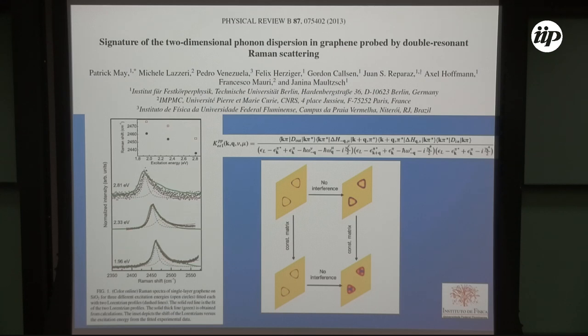And what I have in this calculation is only energy and momentum conservation. So if you take only momentum and energy conservation, you see this point. If you do the correct calculation, it disappears. So this is also related to what Gustavo said in his course. The symmetry may tell you what cannot happen, but sometimes something may be allowed by symmetry. This case is not exactly symmetry, but there is an analogy. Several processes in physics may be allowed by momentum and energy conservation, and may not happen in this case because of the matrix element calculation.